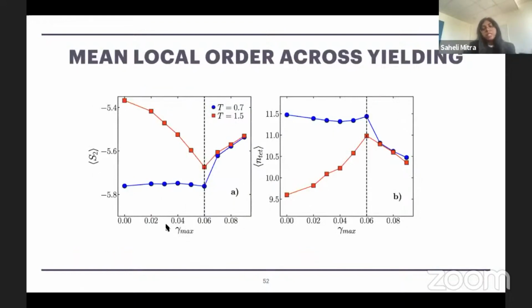We see that below yielding, in the absorbing state, if I am starting from a high temperature glass, the number of tetrahedra increases and the S2 decreases. That means when the system is annealing, the local structural order in the system is increasing. However, for the low temperature glass, we don't see any appreciable change in the absorbing states. So structurally, they are quite similar. Above yielding, however, just like energy, we see that irrespective of their initial temperatures, the system reaches the same structural order state.